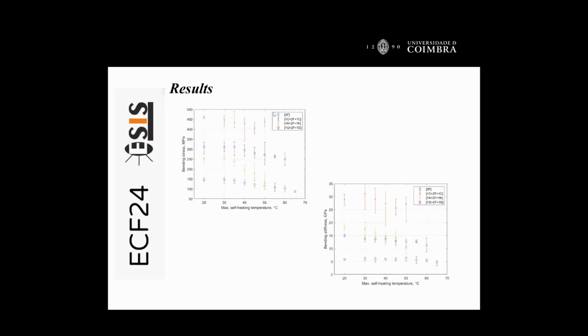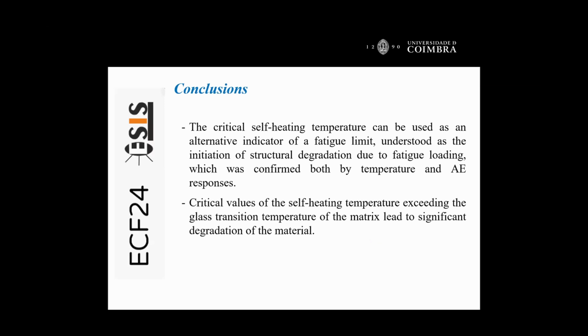Okay, concluding, we can observe that with increasing temperature, we get much closer to the Tg of the resin, and we have effects on the mechanical response of the materials. We can observe that the bending strength decreases, and the bending modulus also decreases. In conclusion, we can say that the critical self-heating temperature can be used as an alternative indicator of the fatigue limit, and as the initiation of structural degradation due to fatigue loading, which was confirmed by temperature and acoustic emission response. Critical values of the self-heating temperature exceeding the glass transition temperature of materials lead to significant degradation of the material.